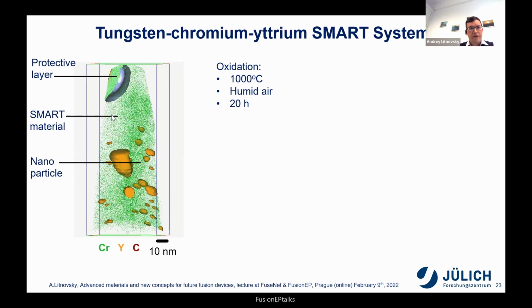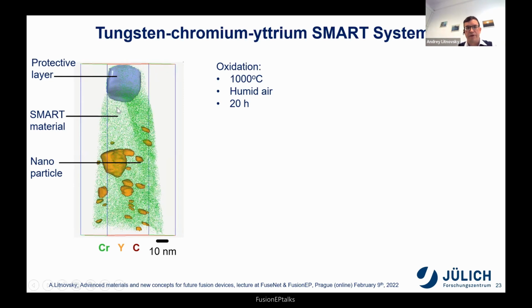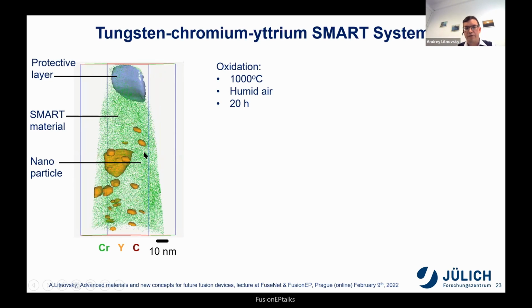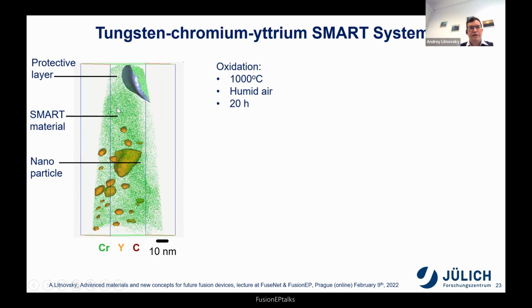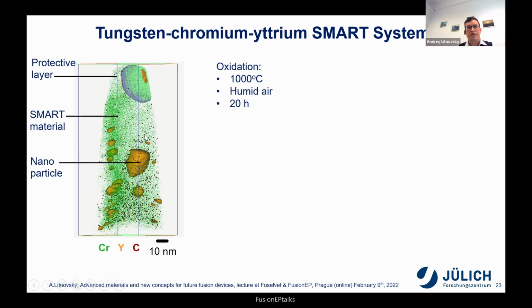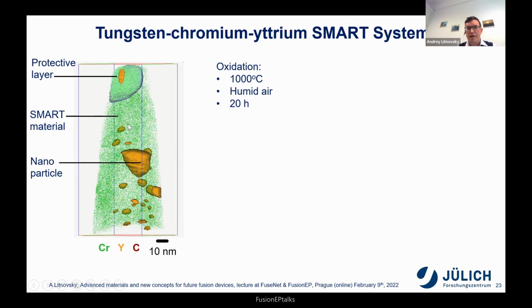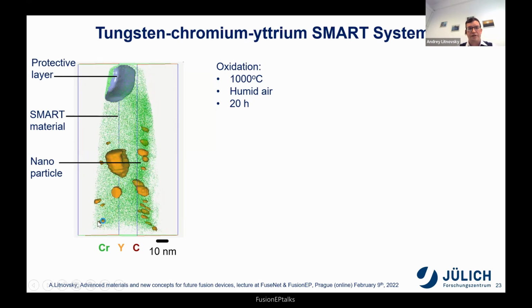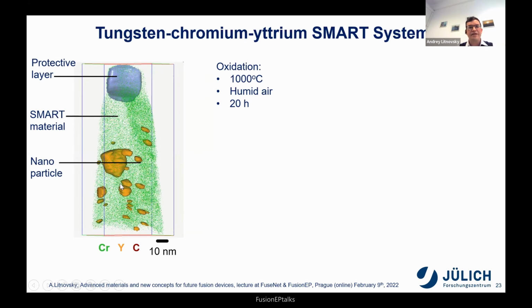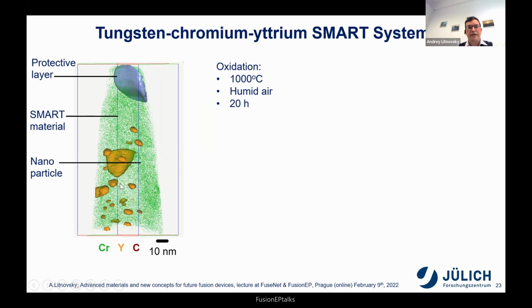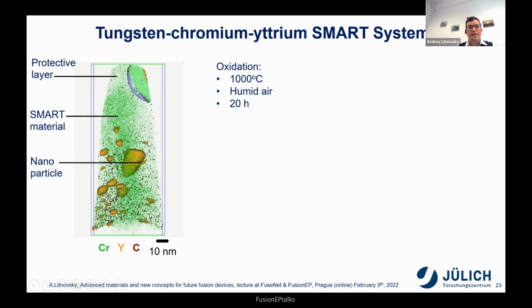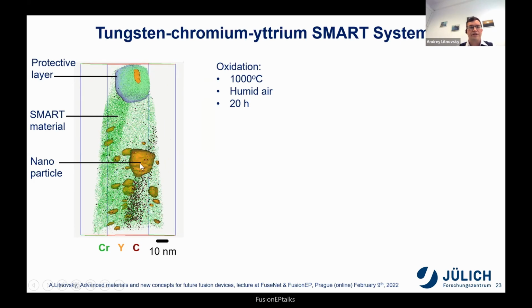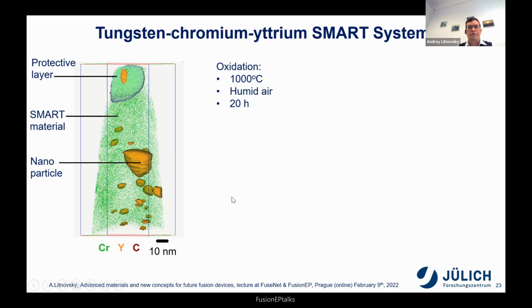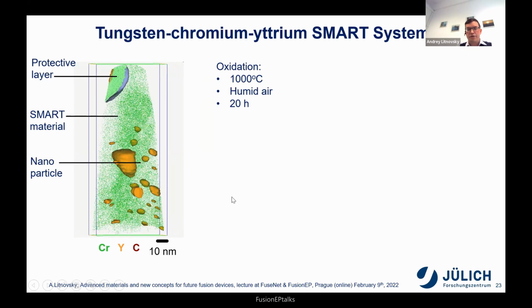Each of these points is one atom. So it's all quantitative. It's not really only a movie. So one can see the bulk of the smart material, the chromium. Tungsten is not shown because otherwise you will not see anything. So this is the chromium inside, and this is the yttrium, which is located in the grain boundary. You can see right now the grain boundary. So this is a yttrium nanoparticle, 10 to 30 nanometers. And this is all quantitative.